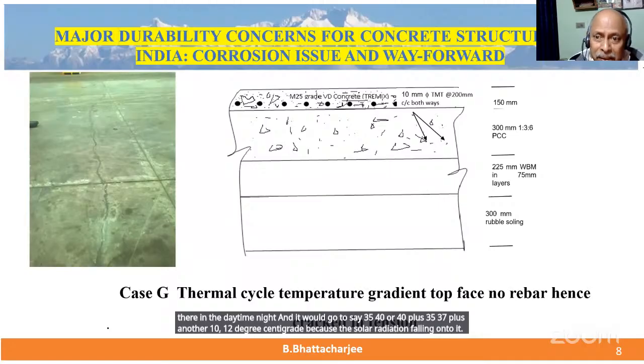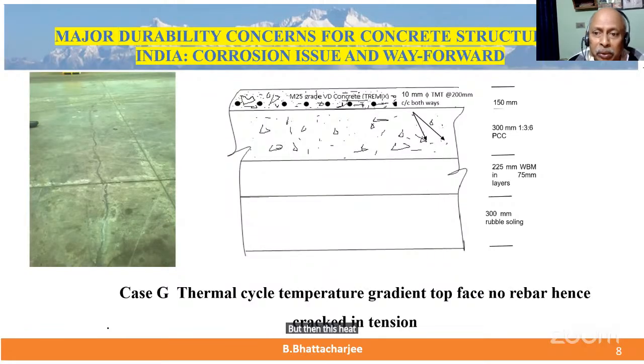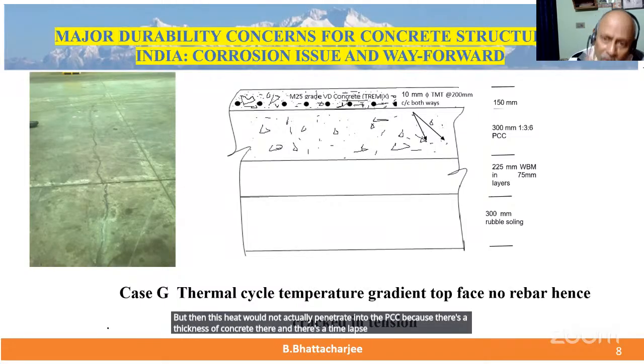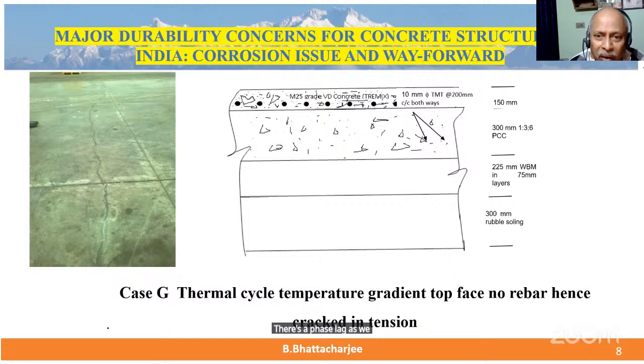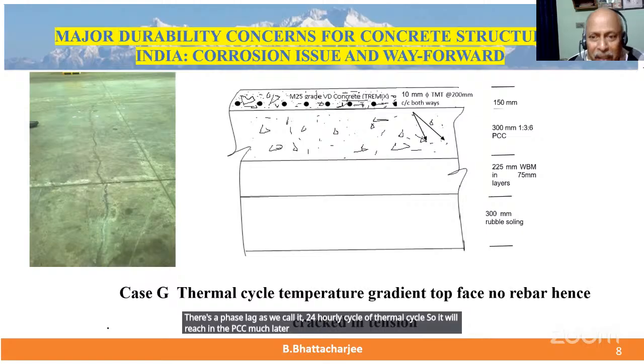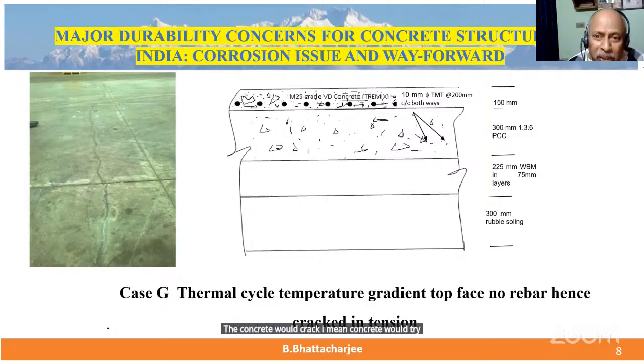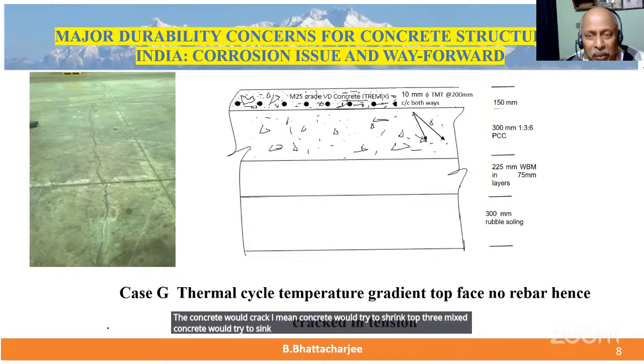But then this heat would not actually penetrate into the PCC because there's a thickness of concrete there and there's a time lag. It will actually penetrate in the night, right? There's a phase lag, as we call it, in the 24-hourly thermal cycle. So it will reach the PCC much later and it will be relatively in an expanded state. But by early in the morning, the concrete would crack. The top Trimix concrete would try to shrink, but it would not be allowed to by the bottom system. And it caused cracks parallel to the groove that they had cut in. They did not cover it. Next time onwards, they did cover, of course.